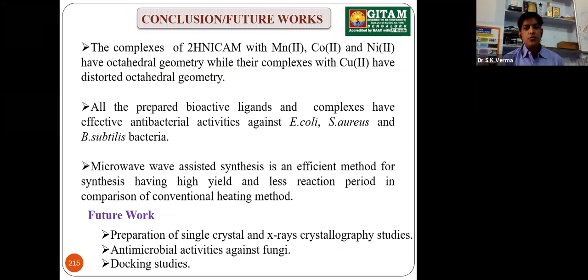Conclusion and future works. The complexes of 2-hydroxynicotinamide with the 4 metal ions have octahedral geometry, while the copper complex has distorted octahedral geometry. All the prepared bioactive ligands and complexes have effective antibacterial activities against E. coli, S. aureus, and B. subtilis bacteria. Microwave assisted synthesis is an efficient method for synthesis, having high yield and less reaction period in comparison to the conventional heating method.